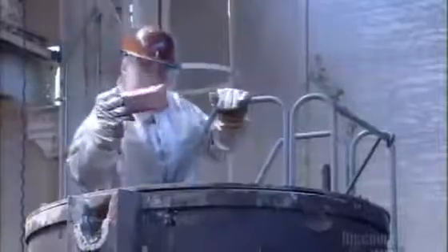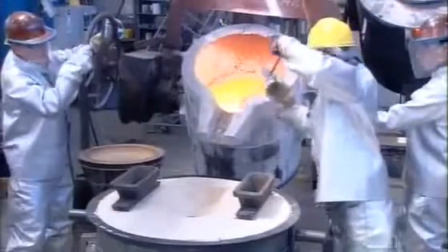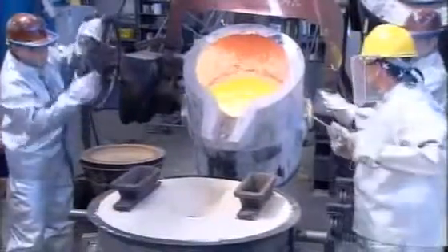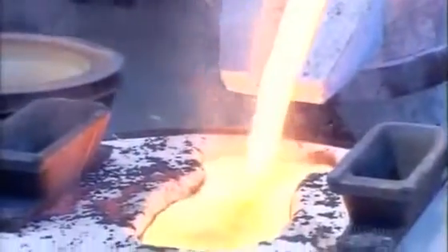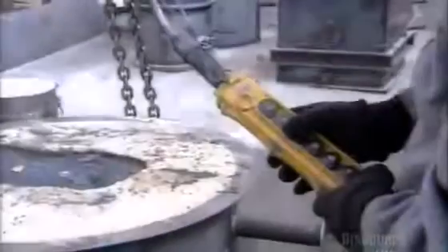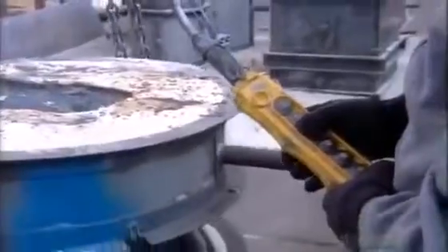Melting enough bronze ingots for an average-sized bell takes about 2 hours. To get a smooth enough consistency, the furnace has to heat the metal to about 1200 degrees Celsius. For a quality casting, they must pour the bronze in one continuous flow, no stops and starts. The funneling basin they made in the sand prevents overflowing. The bronze takes about half an hour to solidify and up to 24 hours to cool.